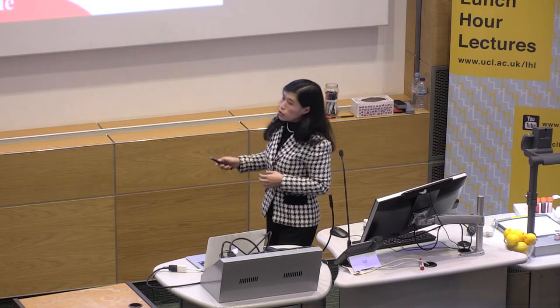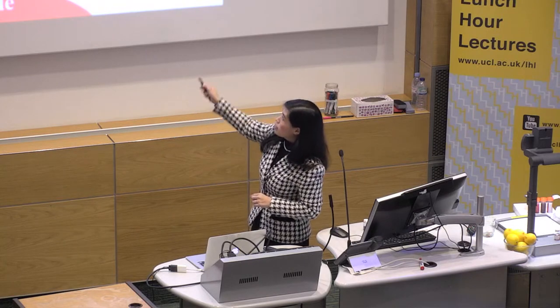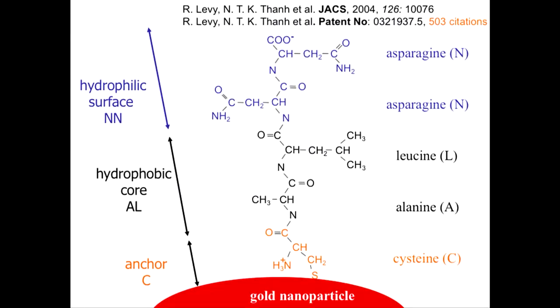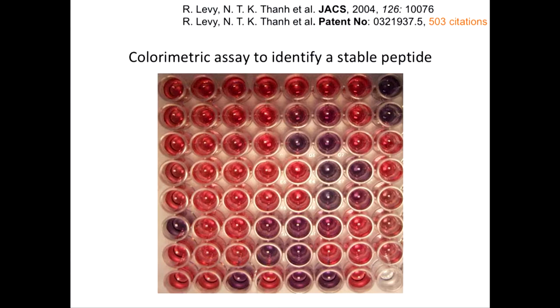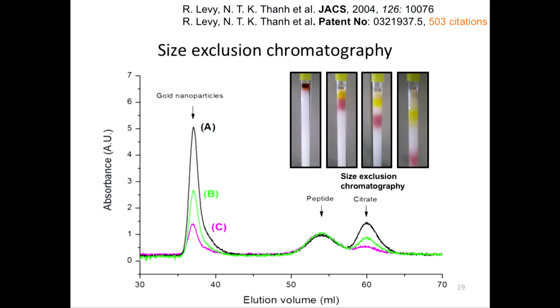The moment you add salt into the citrate nanoparticle, you're screening the charge, and there is no charge repulsion anymore. So that's why the color changes from red to blue. But if you add the egg white, you add this buffer layer of steric stabilization, then when you add the salt in, it doesn't have that effect. So that is very basic when you do this stabilization of the nanoparticle. And again, we're using the colorimetric assay to identify which protein or which antibody or which peptide or polymer stabilizes, based on the very simple effect of the color change.